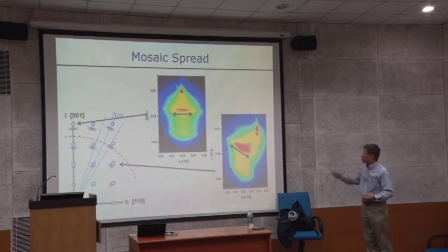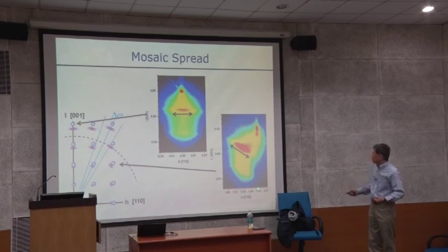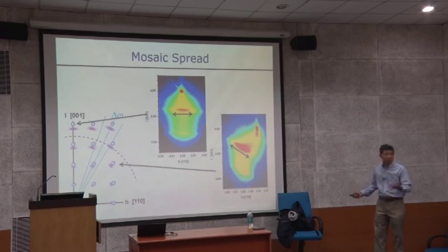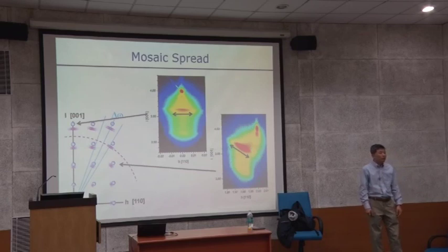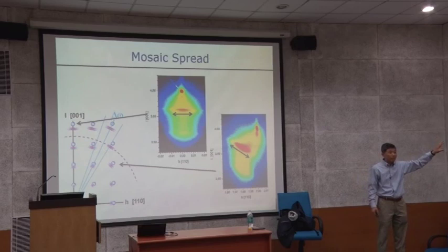So just looking at this, draw the line here. Draw the line here. You get a peak. Nothing, one peak and peak. But if you draw the line from here to here, you miss this peak. You understand? Say I just want to run powder diffraction on a thin film that looks like this. You scan along that direction, you will miss this. So then you don't see the thin film peak. Okay, then it looks like, oh, we have no thin film. But it's not so. The thin film peak is somewhere around here, but you are missing it.